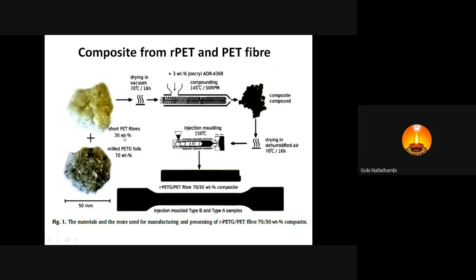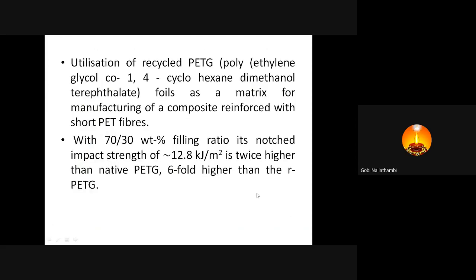Here they took 30 and 70, then dried in vacuum, then they placed these two to make a preform. Then this preform is again passed through injection molding to get a final product. So this is the final product. Then this is the dimension or shape used for measuring its tensile property. The 70-30 filling ratio is notched. Impact strength of 12.8 kilojoule per meter square is twice higher than the native PETG, six-fold higher than the RPETG.